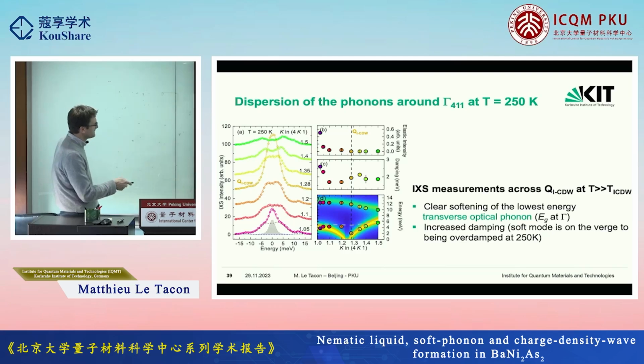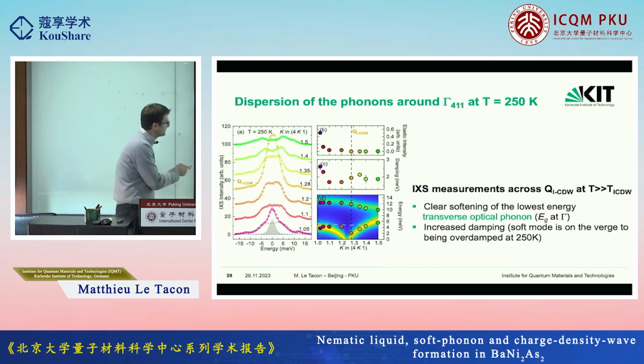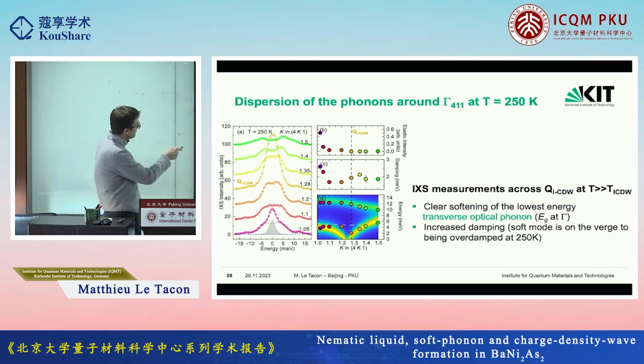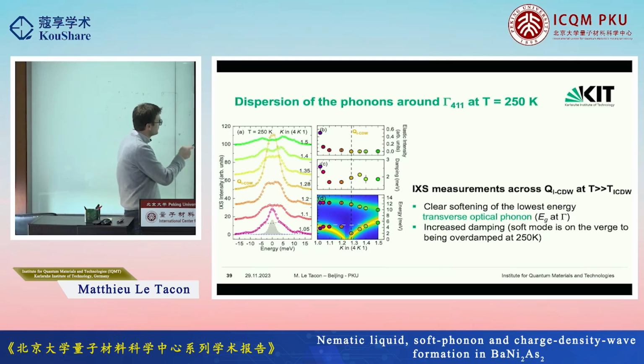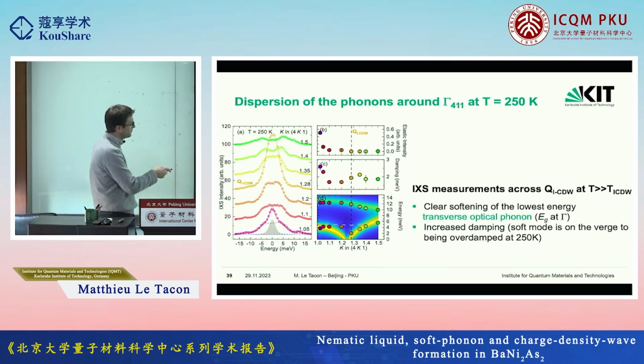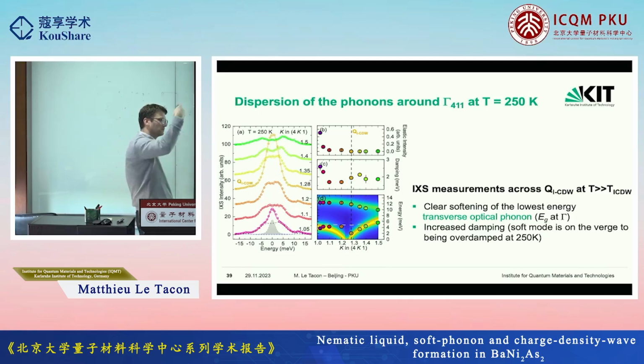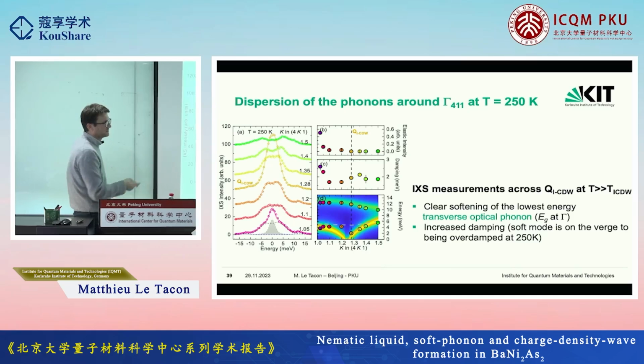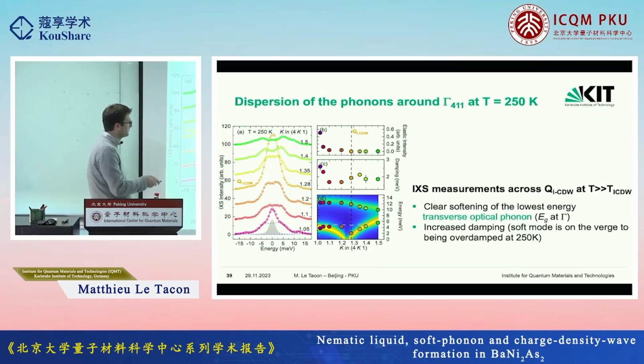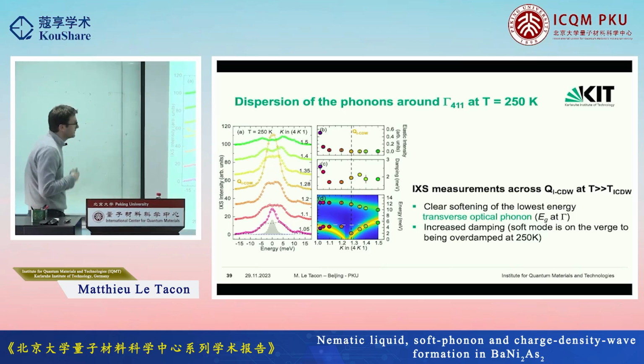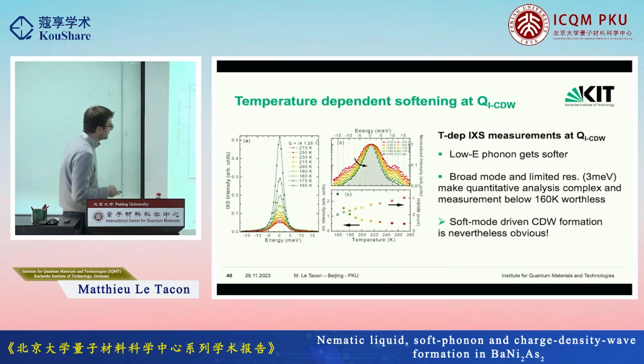And what's interesting is that at the wave vector of the incommensurate charge-density wave, you can clearly see, well above the transition, that the phonons are very soft. And because of this 1/omega in the scattering cross-section, when the phonons are very soft, the intensity becomes very large. So we can fit that and we can follow this and then try to look at this as a function of temperature.